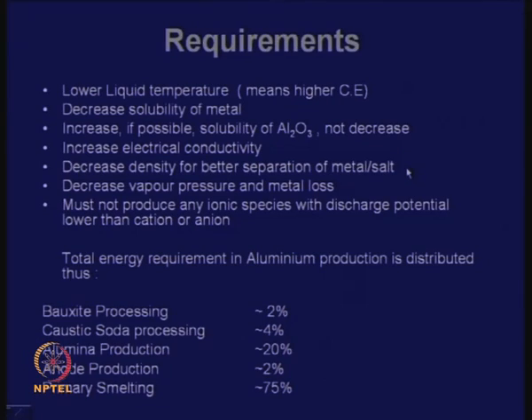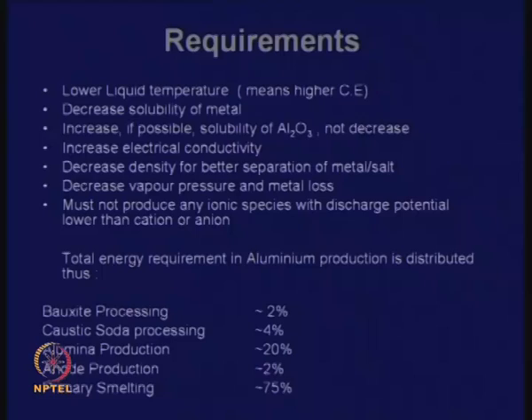Now, if we increase alumina concentration, then you need less voltage for decomposition, but increasing alumina concentration in cryolite will mean increasing the density, bringing it too close to aluminum for good salt metal separation. So, these are contradictory requirements. We do not want too high an alumina concentration, because then the density will go up. So, we want to decrease density for better separation of metal and salt.